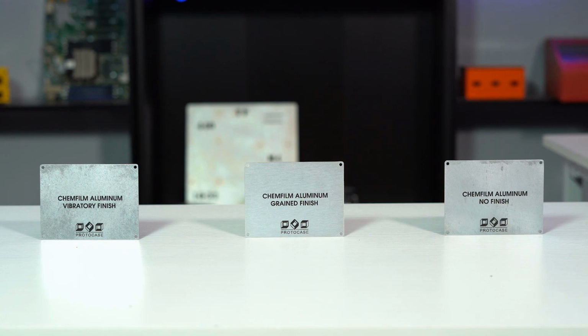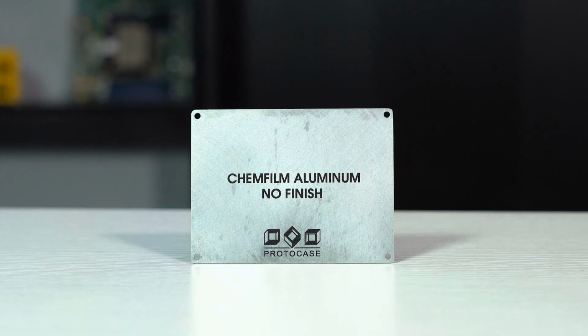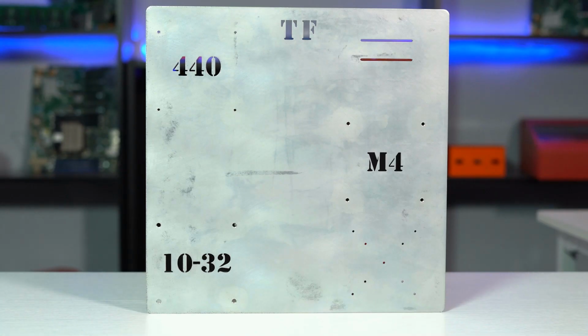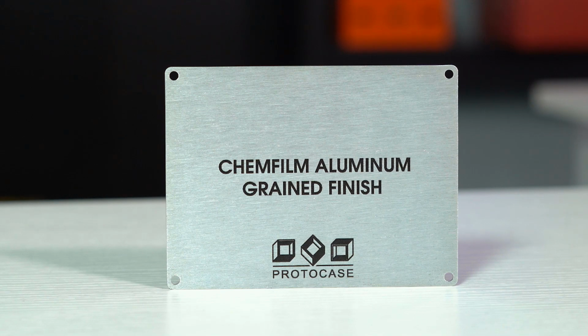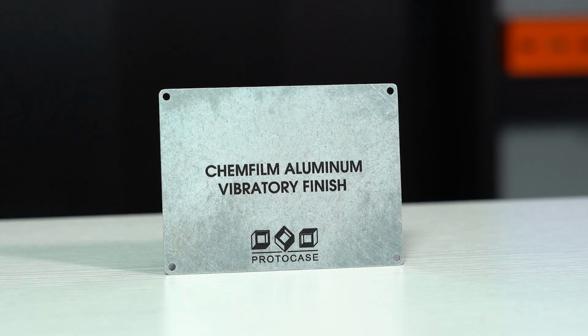One caution about chem film: we do not recommend applying chemical conversion coating to aluminum parts that have no additional finishing applied to them. Bare metal aluminum parts with no finish will have surface scratches, swirl marks, and blemishes. And once a no-finish part has been treated with chem film, that chem film coating will not mask or hide the blemishes that were already there. So for this reason, we recommend choosing a grain finish or vibratory finish for your aluminum parts before they're treated with chem film.